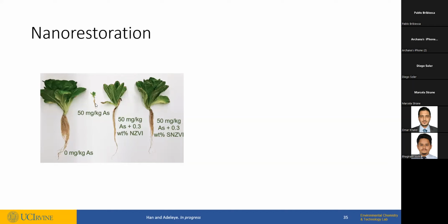And it's making us know that, no, this is not cool. In these other two cases, we also had 50 parts per million of arsenic, but we also had the nanoparticles. So the soil was treated with the nanoparticles before lettuce was grown in there. And you can see that these two plants are way better than without treatment, not as good as the control, but it looks like the nanoparticles are actually doing some good work.